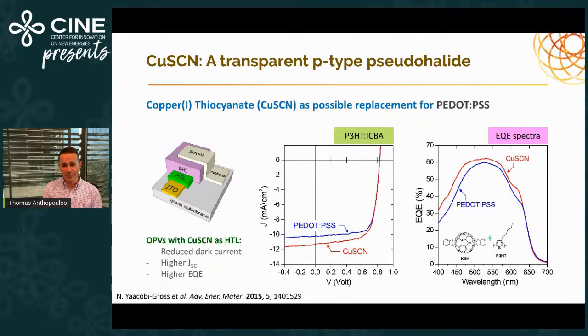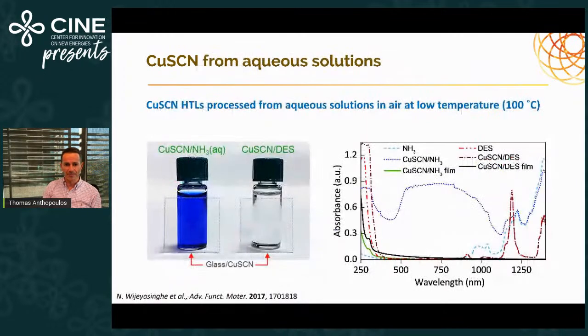This was the first experiment we published at the time, and this is already over 7 years ago, where we took the same bulk heterojunction system, P3HT:ICBA in this case, and replaced PEDOT:PSS with copper thiocyanate. Because we have higher optical transmission, minimizing the parasitic absorption associated with PSS, we're able now to obtain a higher EQE spectrum and essentially a higher short circuit current, as you can see here. And overall, the power conversion efficiency was much higher.